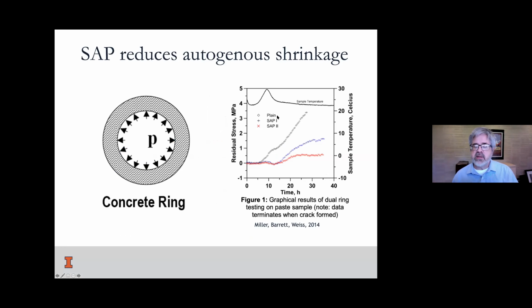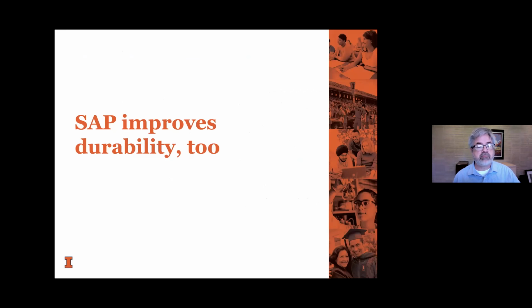And so here are some examples with SAP. We have a plain sample and then 2 different SAPs. And here the stress is building, building, building. And where the data ends is where it cracks. Okay, so it cracks here at about 24 hours. And these SAPs did crack, but later, at 35 hours, and at much lower stresses. So those are nice, vivid examples that SAP is making a difference.